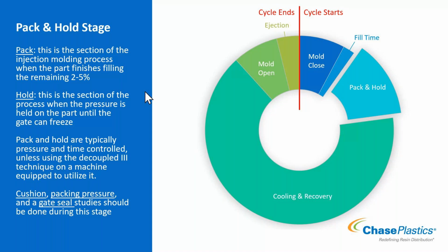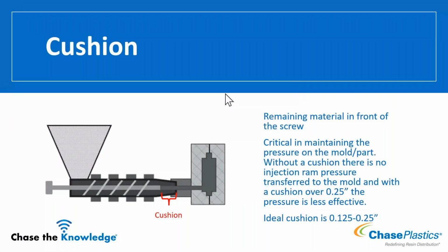So cushion, a packing pressure study, and a gate seal study are the scientific molding steps that can be done in this phase. It's so important to have a cushion. I just want to talk about it quickly. It's not a study that we necessarily need to do. We like to dial in the cushion so that we get somewhere between 1/8 and 1/4 inch of material left in front of our screw to pack off of, or to use for packing at the end of our cycle. So we should end packing and holding with about that much molten material left in front of the screw, 1/4 to 1/8 of an inch.